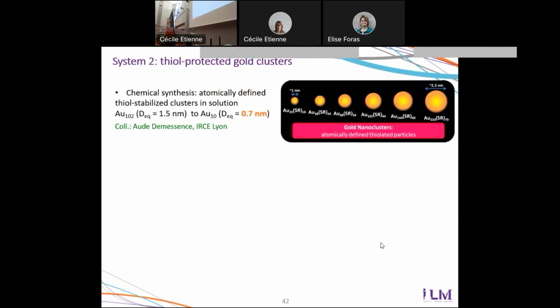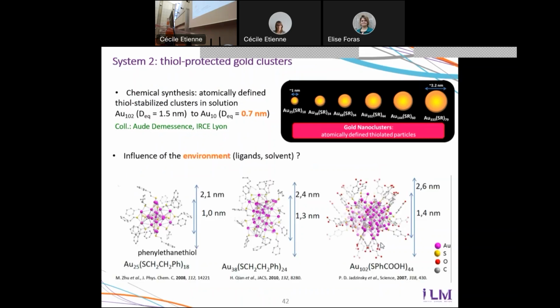So the second attempt in this domain, more recent, was done this time with chemically produced nanoparticles made by our colleagues from Lyon. So the chemists are able to do very nice objects. They can do gold nanoparticles with a precise number of gold atoms. It can be 25, it can be 38, it can be 68. This number is perfectly known. However, the complication coming with this synthesis is that it's not pure metal, pure gold nanoparticles. There are ligands around them, and actually the size of the ligands is close to the size of the gold core. So one has to remember in the modeling not to forget the presence of these ligands.